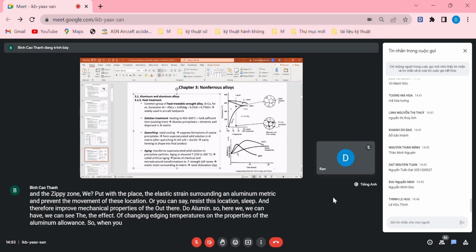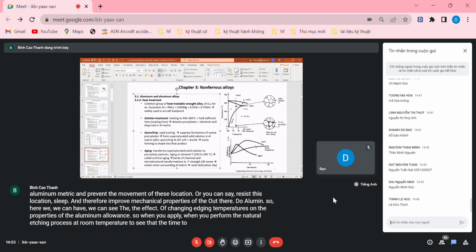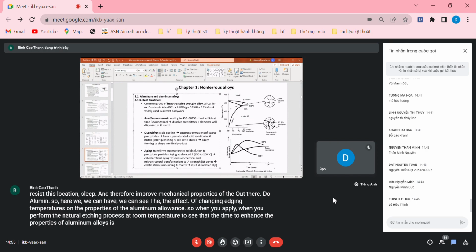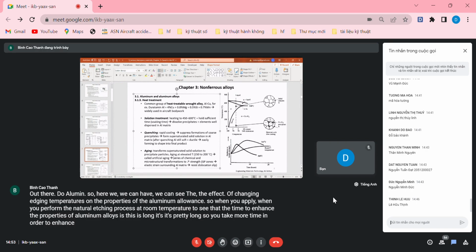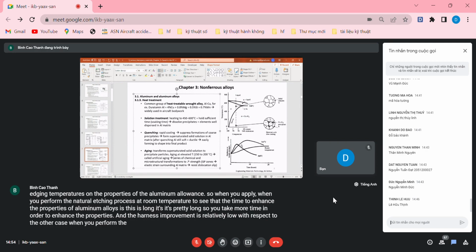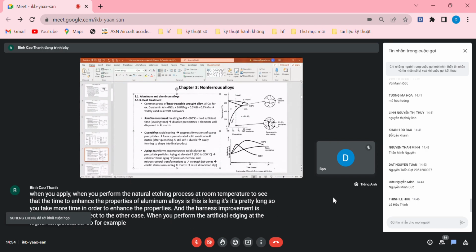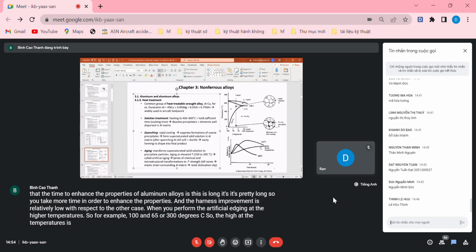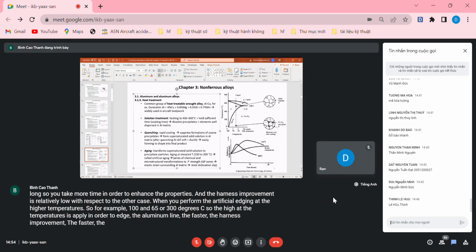When you perform the natural aging process at room temperature, you see that the time to enhance the properties of aluminum alloys is pretty long. So it takes more time to enhance the properties, and the hardness improvement is relatively low with respect to the other case when you perform artificial aging at higher temperatures, for example 165 or 300 degrees C. So the higher the temperature applied to age the aluminum alloy, the faster the hardness improvement.